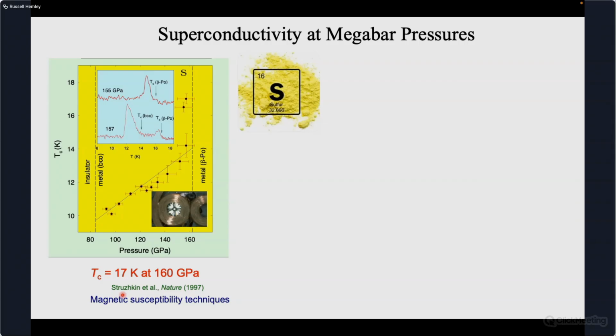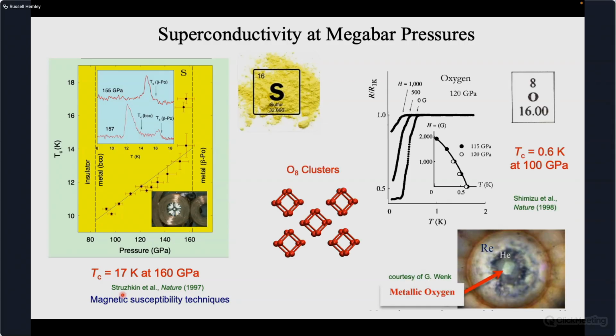which at the time was the highest TC for an element. Other elements were looked at by colleagues, for example in Japan, who found that gaseous oxygen, if you compress it, also becomes a superconductor, albeit a fairly low TC material, but at roughly the same kinds of pressures of 100 GPa, and it goes through very interesting intermediate states. In fact, these molecular structures emerge before it goes into this superconducting state. So this led to a series of studies that we carried out over the years, mixing different components together to look at the possibility of doping or using chemistry combined with high pressure to make this hypothetical material.